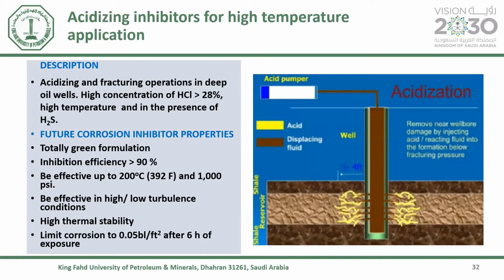So another important challenge for the future will be a corrosion inhibitor for high temperature acidizing oil and gas wells. So during acidizing, high concentration of mineral acid are pumped into the well. So, and this can lead to corrosion. So corrosion inhibitor is normally added. So how can we develop corrosion inhibitor that are totally green, more than 90% effective, and can protect up to 200 degrees Celsius and up to 1000 PSI or more? Could be effective in high turbulent flow or low turbulent flow conditions, high thermal stability. And these are some of the challenges that will need to be overcome.